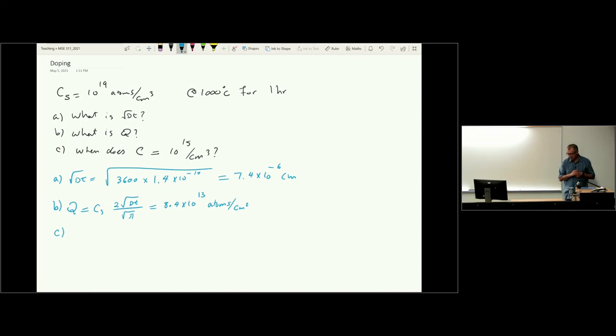Okay. So what I need to do now is that I have the equation for C of x and t, which is the one based on the error function. Let me just go back one step. I can see you have this equation. So C of x and t is CS, the surface concentration, times the complementary error function of x over 2 square root dt, right?